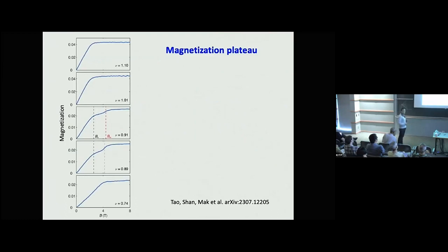And then we look at the magnetization, or the MCD, as a function of the magnetic field at different doping densities more carefully. This is electron doping of the Mott insulator. You can see pretty much a paramagnetic response. Then this is very close to the Mott insulator. Then this is hole doping into the Mott insulator. You can see the emergence of an intermediate plateau in the magnetization. And then finally, if you dope too far away from the Mott insulator, the plateau is also gone.